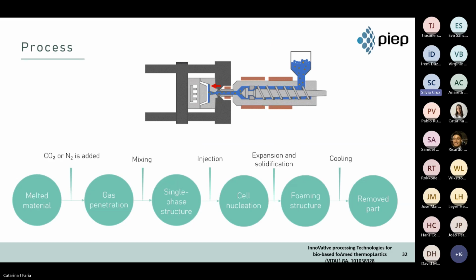And how does this work? So the foaming agent used in the process could be either physical or chemical, as Johanna mentioned. In the case of physical, it could be nitrogen or carbon dioxide. In case of chemical foaming agents, they could be inorganic or organic, such as calcium carbonate or talc.